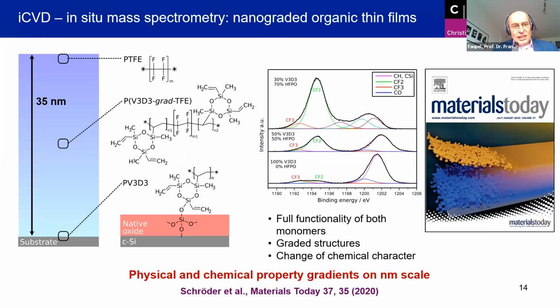Another approach which we are very excited of recently is to make gradient layers with this iCVD technique. Like for wet chemistry, you can make copolymers of 2 monomers, but here we can, during deposition, vary the gradient from monomer A to monomer B. So we can go all the way, for instance, from a hydrophilic to a hydrophobic surface. We can vary physical properties. And we recently demonstrated in a cover story in Materials Today that we also have control on the nanoscale.